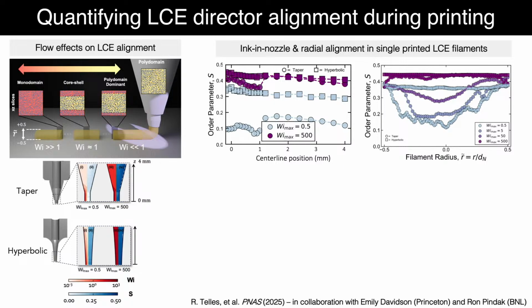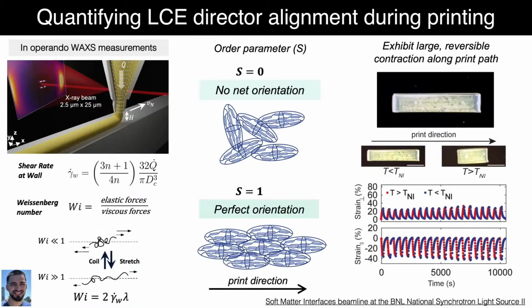And so what we see here, if we look at the center line position, this is going up into the nozzle from the outlet up to 4 millimeters in height. We can see that depending on the Weissenberg number, which I totally blew past, so let's go back. This is just a balance of elastic to viscous forces. This is a scaling parameter. When this parameter is much lower than 1, we would expect isotropic features to be printed, no shear-induced alignment. When this is above 1 and substantially so, we would expect these long oligomers to stretch and become aligned. And that's what we really showed there. And this Weissenberg number is proportional to the shear rate at the nozzle wall, and that measured structural relaxation time that I just showed you, lambda.